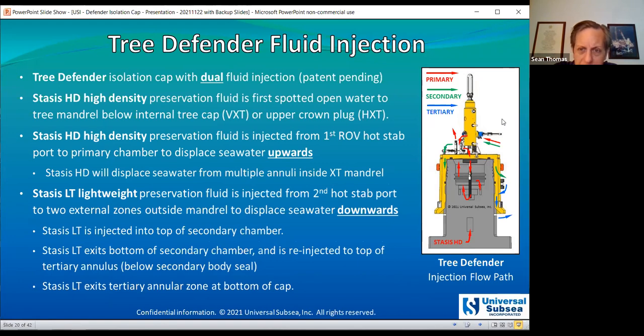So the red arrows there we see for the primary flow path, we're injecting high density preservation fluid. Once that's done, we shift to the second port of the hot stab receptacle, and we inject lightweight fluid into the external, the secondary chamber and what we call the tertiary annulus. That is the two zones on the outside of the mandrel. This provides the most effective system to displace seawater from the tree mandrel internally and externally, and create fully protected zones with the preservation fluid.